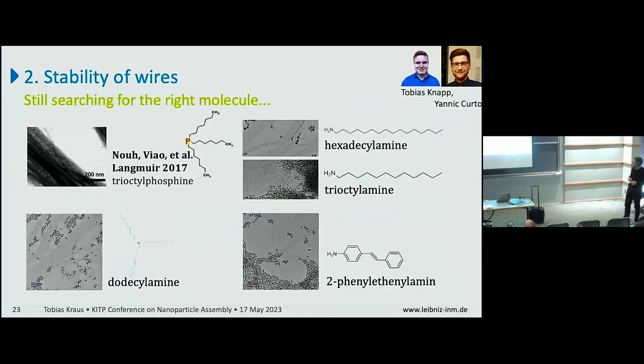However, historically, many people have tried that, our group and others. There are some reports. So for example, in 2017, a French group reported that a phosphine would increase the stability a bit. I think it at least doesn't decrease it very much, but the difference for us doesn't seem to be very large. We have been able to put a few other molecules on these surfaces, in particular amines. It turns out that if you put thiols, which is the trivial idea probably for a chemist, it immediately breaks them completely, which probably again has to do with the fact that the bond to the gold plays a larger role than one may think.